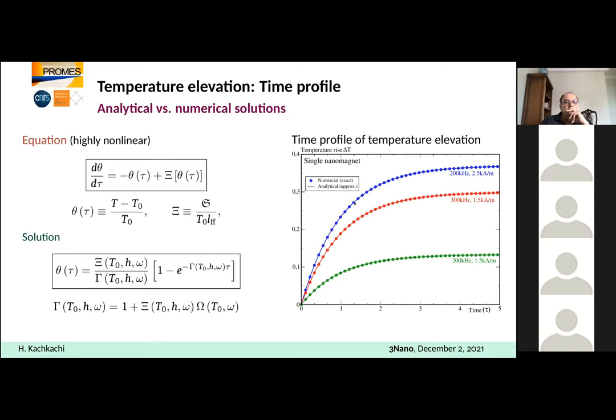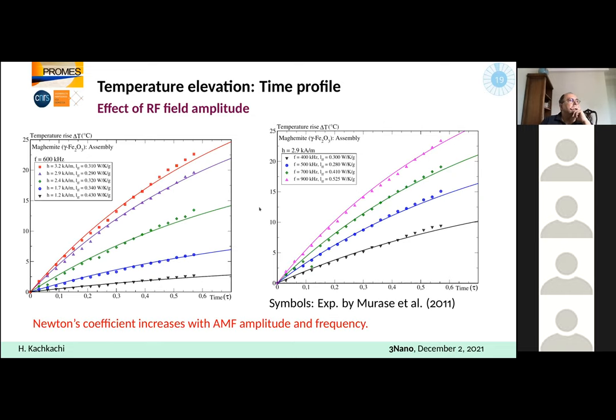Now, this is a comparison with experiments. I just took some data from the results by Murase, published in 2011. So what we have here is the temperature rise in degrees Celsius as a function of time. And by fitting the experimental results, we can obtain this Newton's coefficient as a function of the amplitude of the AC magnetic field, and here as a function of the frequency.